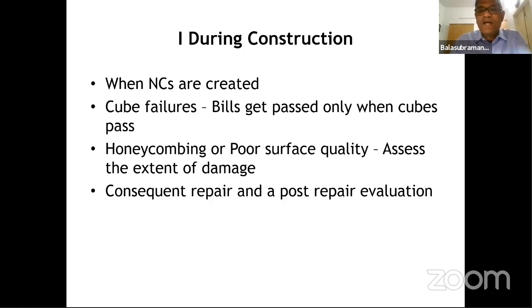That's the reason why you have to take cores. And the contractors are a little hesitant to take cores because they know the cubes are done with so much care, and they fail, so a core may also fail. Even though there is a buffer of 85% of the fck, they are still not very comfortable. So they bring a rebound hammer. With the rebound hammer they are very comfortable because it predicts the strength on the higher side. So the NC is closed and then the bill gets passed.